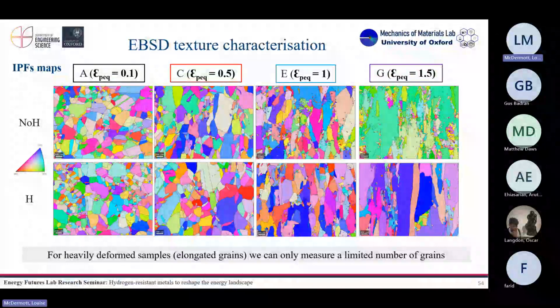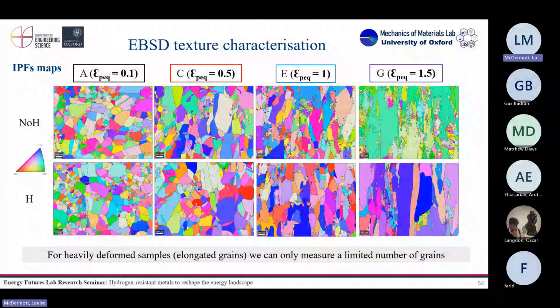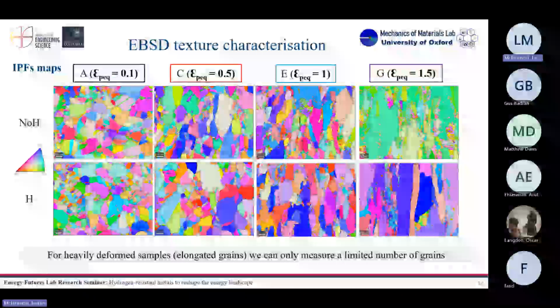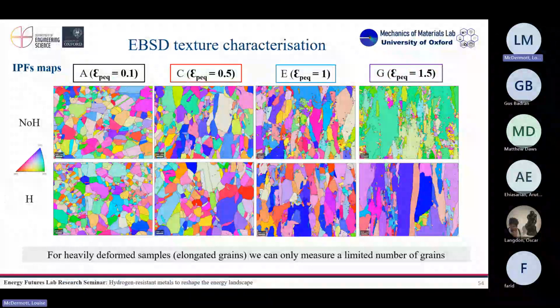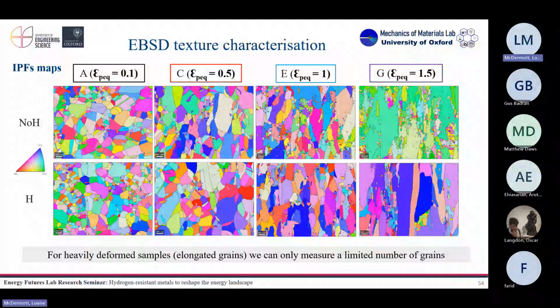So we did EBSD scans for all the deformations that we studied, with and without hydrogen, but we realized that it was going to be very difficult to get statistically robust conclusions from here. As we deformed the sample, we have very large, elongated grains, and we cannot really capture the behavior of a lot of grains. For EBSD to be representative, we need to analyze at least 10,000 grains, for example. We said, okay, it seems we see something, but we cannot really claim something.